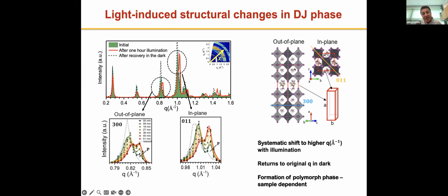And so we looked at these specific planes, the 300 and 011, which is the in-plane axis. If you look at these two planes, which are shown in circles here, what we found is that we could actually track this effect. So you can see that with light, there is an increase in the Q values in both cases. And then over time, you keep doing this.